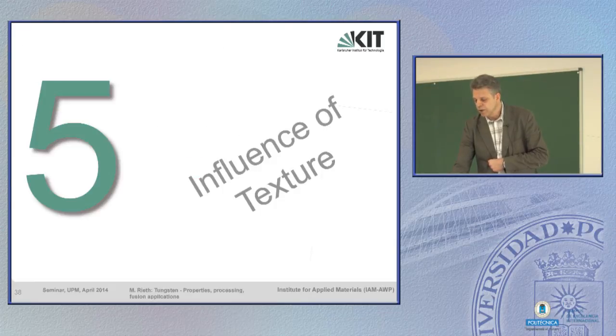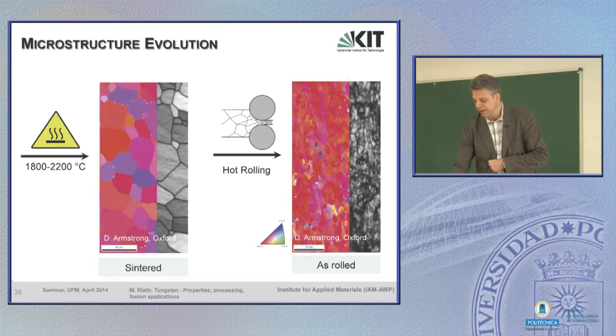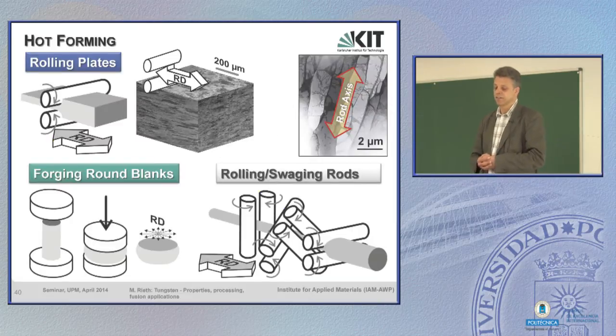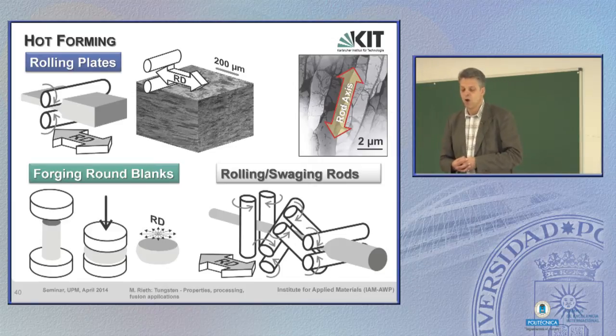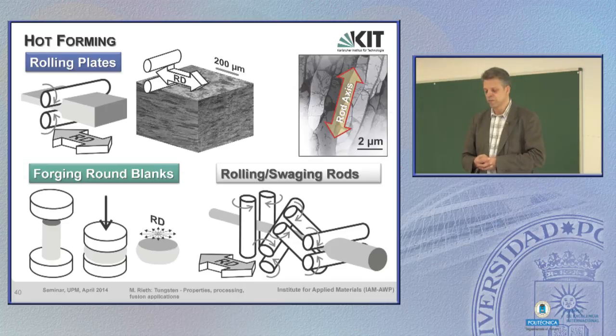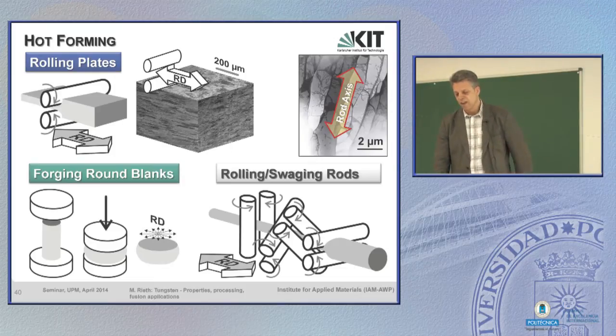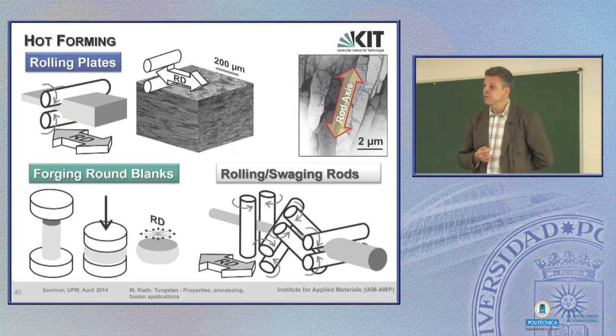Now let's compare this to rolled or formed tungsten, which shows a specific texture. On the left-hand side, we see sintered tungsten, the typical polycrystalline microstructure, with grains homogeneously distributed. On the right-hand side, the same material as rolled. In general, hot forming in tungsten is performed by rolling, so for plate fabrication, or forging. That's less common, but you can still produce semi-finished products like small round blanks. And of course, rods are also fabricated mainly or most often by rolling or swaging.